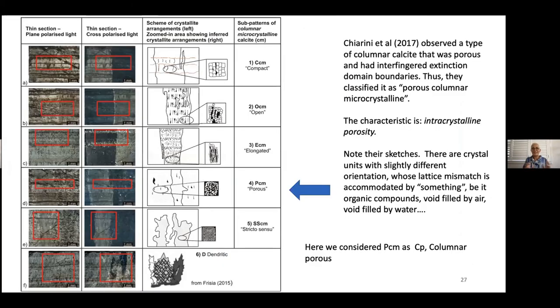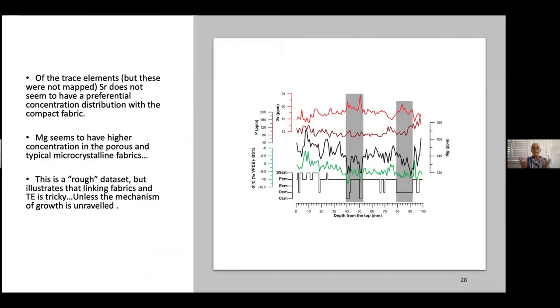In 2017, with Veronica Chiarini looking at some stalagmite from Bosnia, we already had the idea, which is illustrated in this graph. You notice the tiny little crystals slightly mismatched with the voids. At that time, I didn't even consider the non-classical pathway exactly. Then I stepped into what's called mesocrystals, and they look exactly the same. So you have lots of nanocrystals arranged together, and in between you have organic matter. That's a very nice way to entrap the organic matter into your calcite. It doesn't go in the lattice, it goes between nanocrystals.